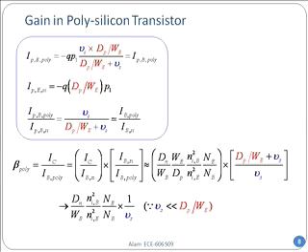But it turned out they just tested it. And amazingly, it turned out that it has a gain. The one that was made with the malfunctioning reactor had a gain which was significantly better than anything they were making. As a result, this polysilicon transistor subsequently became the standard in the industry. I have posted a paper on the website about the history, and you can take a look. And this is a very nice story about this whole thing.